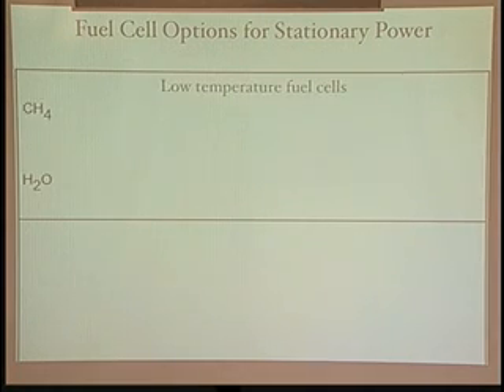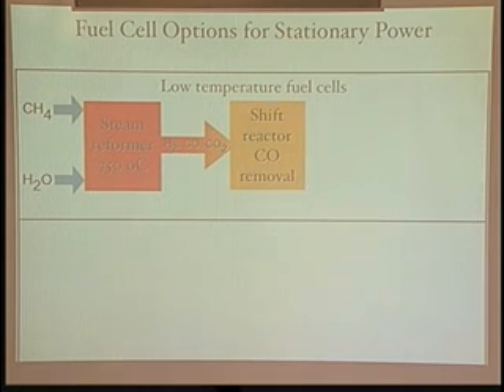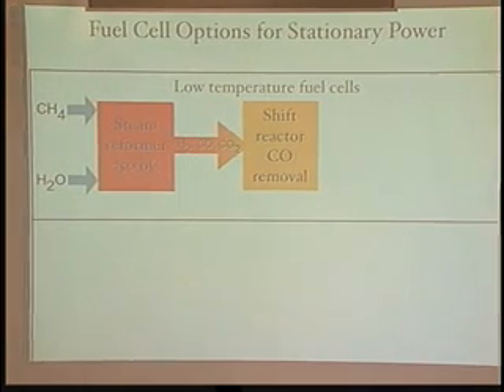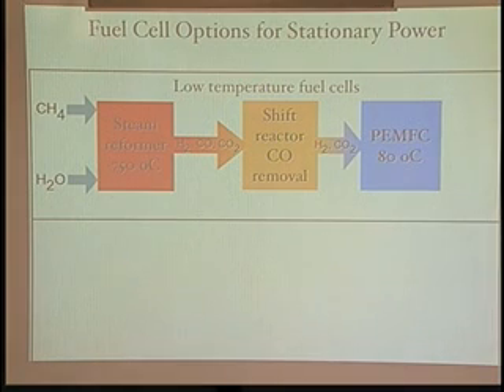There are companies trying to develop PEMs for stationary power. One of the problems is, if you start with methane and water, and you're going to steam reform that, that occurs at a fairly high temperature. And PEMs don't like CO. It poisons the platinum because they operate at low temperature. That means you need a shift reactor to remove the CO and operate the PEM at 80 C. So you're reforming at 750 C, and you're operating it at 80 C. That's a huge efficiency loss.